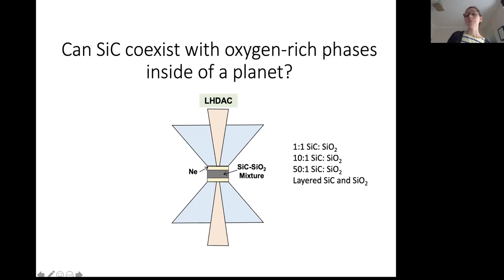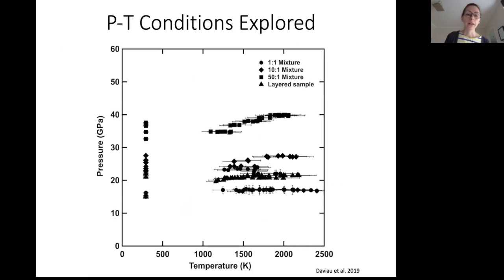And we opted to use different concentrations in order to see if there was a difference with how much silica you had. So we explored a 1-to-1 silicon carbide to silica mass ratio, 10-to-1, 50-to-1, and then we also looked at a layered sample, a silicon carbide layer next to a silica layer. We explored a number of pressure and temperature conditions, with temperatures up to 2,500 Kelvin and pressures between 10 and 40 GPa.